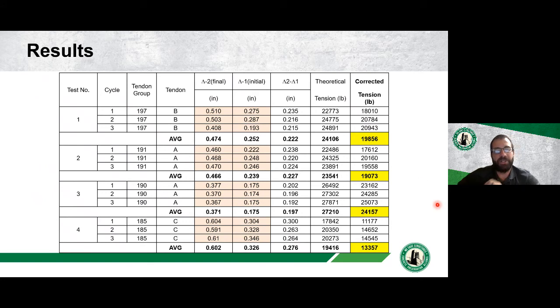And so with the tension in the strand, we can determine if the strands have been tensioned properly. And so you can see here, some of these strands are not tensioned quite to what they should be, especially test 4 at this tendon, clearly not enough load on that tendon. So we were asked on that structure to go out and verify that everything was tensioned properly.